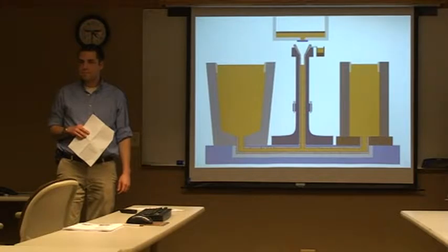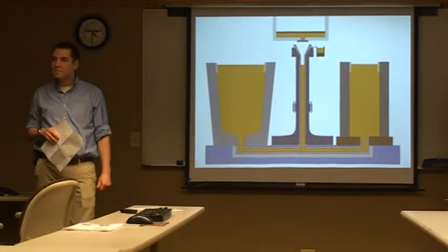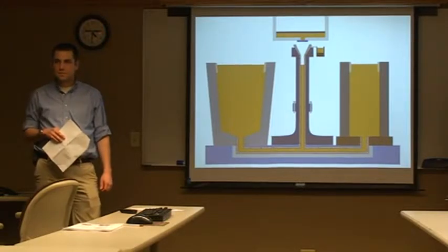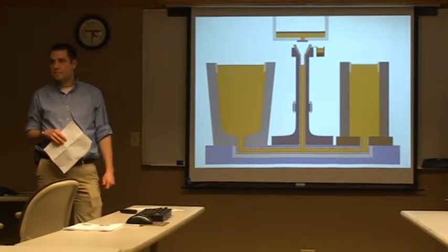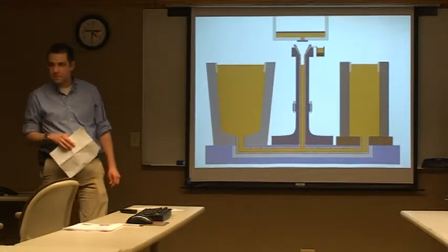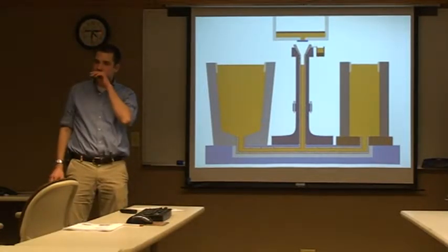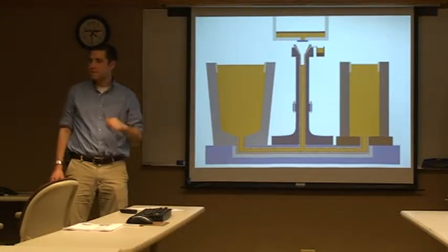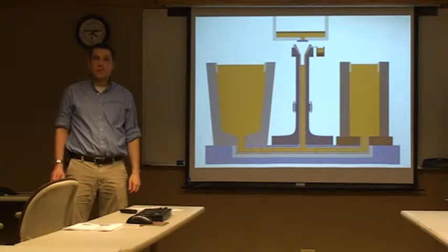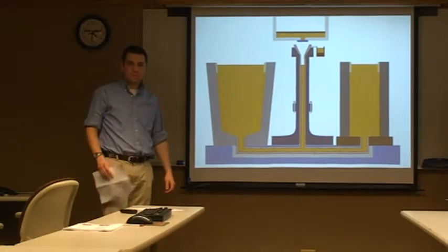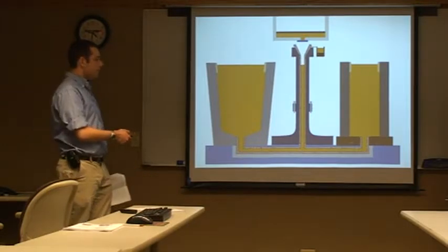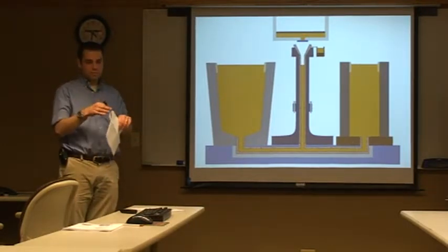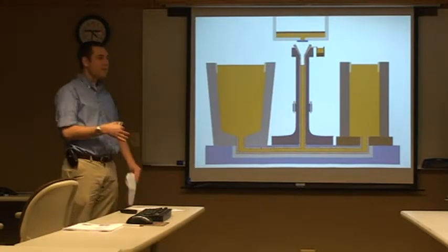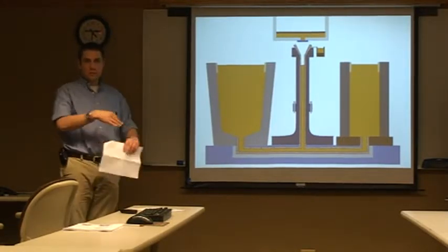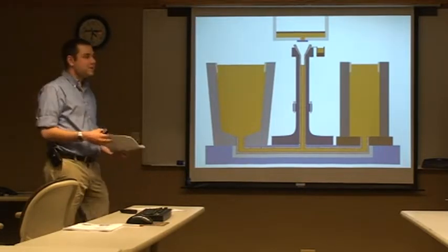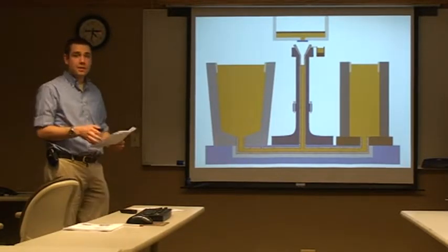So when we set the trumpet brick into the trumpet, we cover the funnel, and then we pack it with just loose dolomite, which used to be sand, but because of silicosis and safety issues with silica, we use dolomite, and it just packs. So really, when we lift that trumpet up, it almost just falls right out. It doesn't really stick unless there's some flashing or something like that. It's the same thing with the runner bars too. We also have slots that are much bigger than what's needed for the ceramics, so we use dolomite to pack them in there loosely, so we don't have any problems with it sticking.